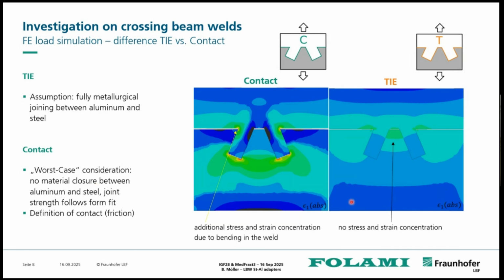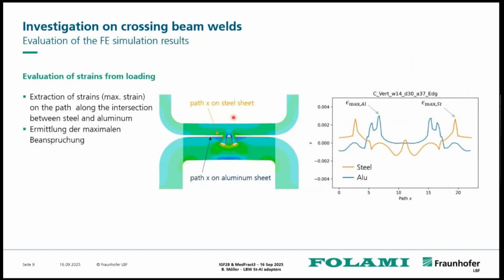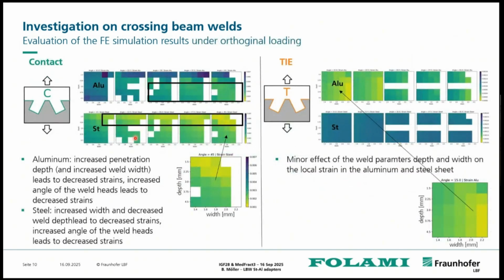So from this, we said there is a path along the intersection of the two materials, and we can evaluate stresses and strains from it. Especially strains are of interest in the aluminum material and the steel material. So blue is the aluminum peak of maximum strain, orange is the maximum strain of the steel material. And if we evaluate this for all of the finite element models and simulations, we get some matrix box plots, as you can see here.